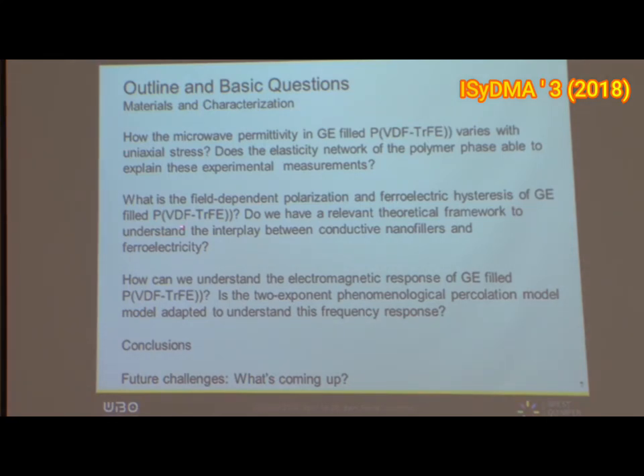Because the PVDF, which is the polymer matrix, is a very good ferroelectric. Well, it's not entirely PVDF because there's a copolymer, which is trifluoroethylene. And the question we want to ask is what is the coupling between conductive fillers and the ferroelectricity of the polymer matrix, because we know that conduction of particles is often detrimental to ferroelectricity.